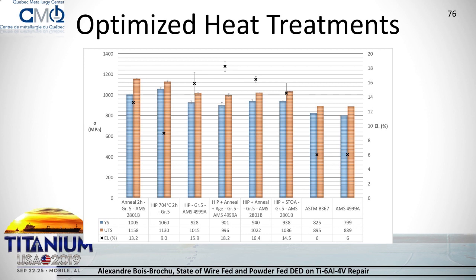So if you look at annealing for 2 hours at 704, you have a yield strength that's above 1000 MPa, and you still have 13% elongation. Meanwhile, if you do the HIP at the same temperature, the strength will be even a little bit higher at 1060 MPa yield strength, and you still have 9% elongation, which is quite above the 6% required by both standards.